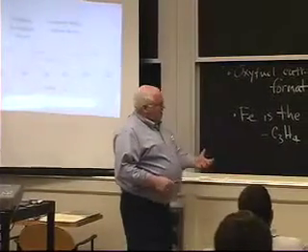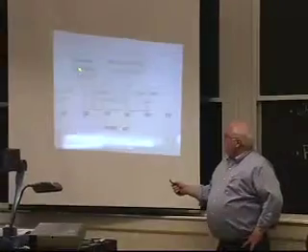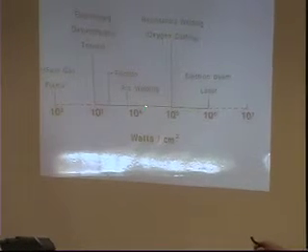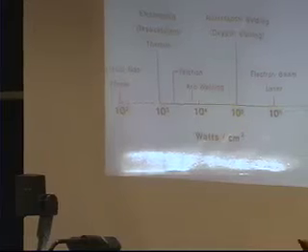Last time we talked about oxy-fuel cutting, and I mentioned that it eliminates the boundary layer by formation of liquid oxide. By eliminating the boundary layer, you go from 10 to the third to about 10 to the fifth watts per square centimeter, almost 2 orders of magnitude, up to 100 times greater heat intensity on the surface.